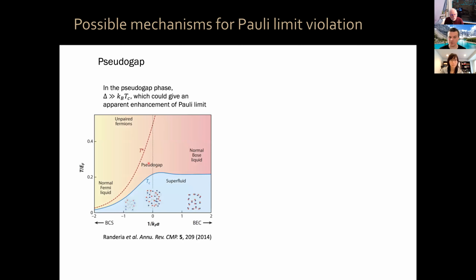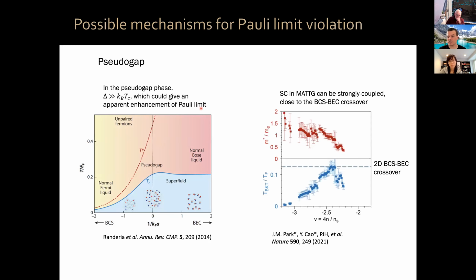Then one last mechanism is the possibility that due to strong coupling superconductivity, you have preformed pairs with a pseudogap, where in that case, the critical temperature has nothing to do with your pairing amplitude, but it has to do with your superfluid density, phase stiffness in your system. However, in our system, we can measure the superconducting coupling strength as a function of filling factor, and we can see that it varies by over an order of magnitude. Okay, we have very strong coupling near this region, but relatively weak coupling near the edge of the domes.